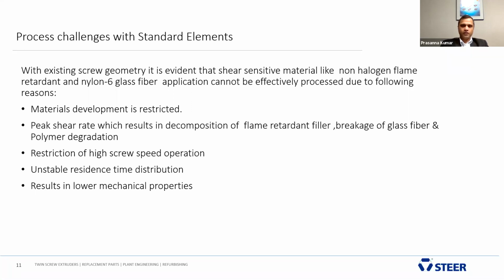As I said, we have extruders which are being built to 1200 RPM, and I'm pretty sure most of the compounders are not utilizing the complete screw RPM because of the process limitation. When we run at higher screw speed, there is also unstable residence time distribution, which also results in lower mechanical properties. These are some of them which we have identified. I'm pretty sure there are a lot more, and we would like your input as well on this.